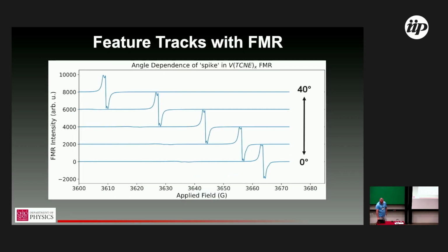But let me start with just the systematics. This is one of the less exciting but more important plots to show: at these high powers, if we rotate the orientation of the DC field, we see the shift in resonance consistent with the anisotropy. Anytime you see something very sharp like this, one candidate is that we've done something terrible in the microwave engineering aspect. Maybe there's some weird reflection or something happening. This is a commercial Bruker EPR, but things break. But this tunes with the FMR resonance, so we think this is something intrinsic to the magnetism. It's not a pure microwave effect. So that's an important sanity check before we push too much further.